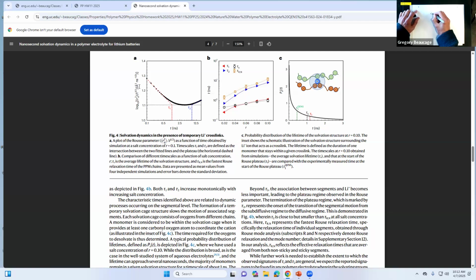So he's got this idea that the mean square displacement, if it's Brownian, for diffusive, is equal to 2Dt. So it's proportional to t to the 1. And then if it's sticky Rouse, then that's proportional to t to the 1/4, and then it's t to the 1/2 if it's Rouse.